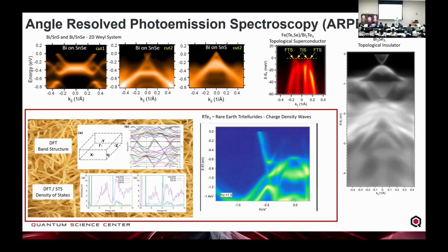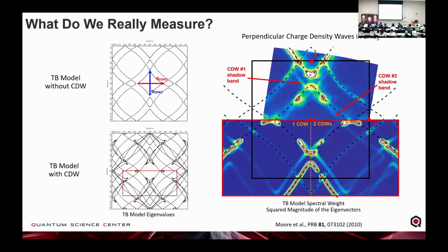Now, another difference is that STM is very localized. You're looking at a single atom. As you do a spectroscopic measurement, you're looking at the local density of states on that atom. Whereas here, our ARPES beam spot is on the order of tens of microns. And so we're looking at more of an average of the electronic structure over a macroscopic scale. And so these are some of the differences between ARPES and STS.